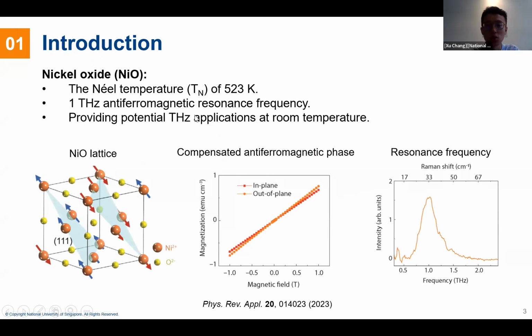The resonance frequency is measured by Raman measurement, and the frequency is shown to be 1 terahertz, the peak around here. So the high Néel temperature and high resonance frequency give nickel oxide potential terahertz applications at room temperature. That's why we are interested in this nickel oxide single crystal.